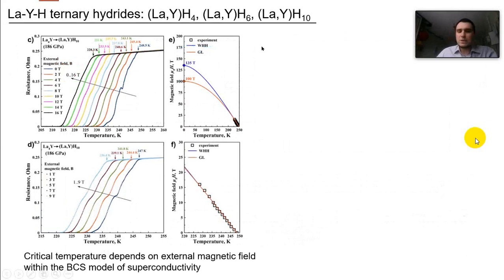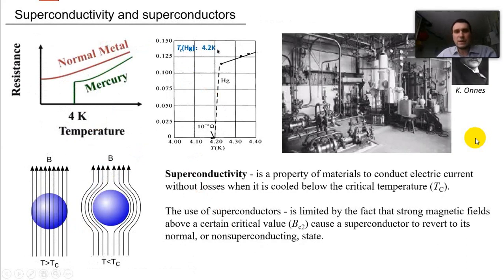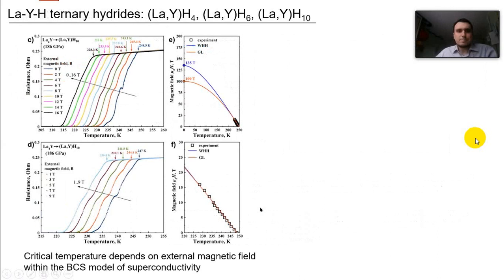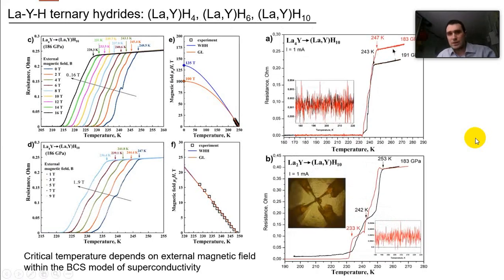So let's look at the parameters. You see here the parameters of mercury. The Tc of mercury is about 4 kelvins. It was the first superconductor discovered. And we can look now at the materials that we discovered here in Moscow. These are ternary hydrides, lanthanum-yttrium ternary hydrides. The composition is (La,Y)H10, so the XH10 group. They are cubic compounds with Fm-3m structure, and Im-3m structure for hexahydrides. You can see that all of these diagrams are about the dependence of electrical resistance on temperature. And you see that at a certain temperature, about 250 kelvins, the resistance suddenly drops and disappears. So the change in electrical resistance is from 1,000 to 10,000 times.